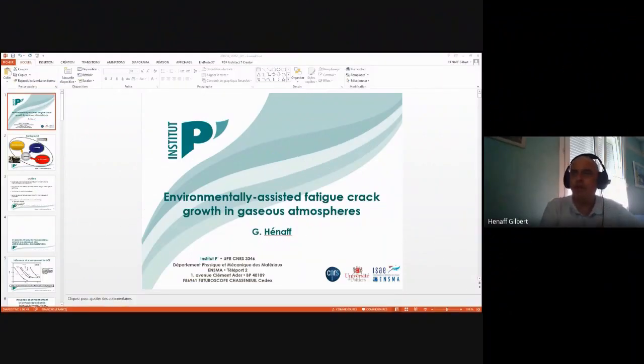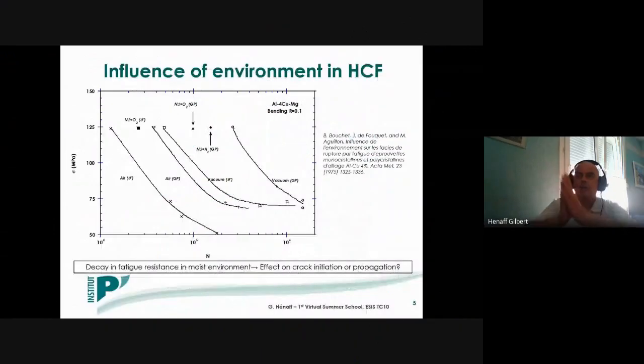Let me move to the first section of the talk about these evidences. On this slide, you have some S-N curves obtained on an aluminum, copper, magnesium alloy. So maybe I can start from this slide, presenting S-N curves obtained on aluminum, copper, magnesium alloys loaded in bending with two different heat treatments corresponding to different hardening precipitates, namely theta double prime or Guinier-Preston zones.